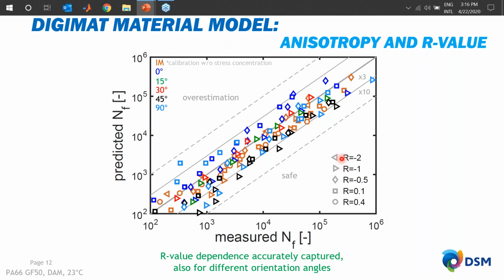Then you can see that for different R values, highlighted with different types of markers, and for different orientations, highlighted by all the different colors, we can describe our entire data set well within this factor 3. So that means that we have a material model that can capture the influence of anisotropy plus R value very accurately for all the data that we have measured and used for these input calibration curves.